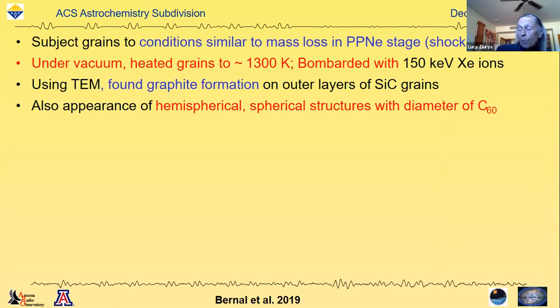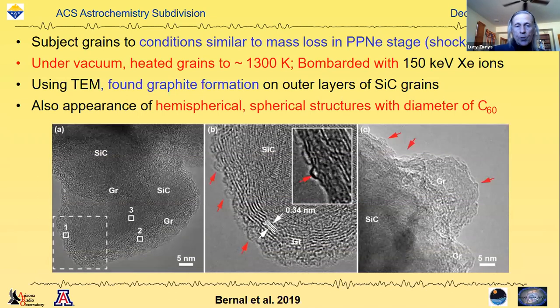So what did we want? Basically, what we wanted to do was subject those grains to conditions similar to what happens in the protoplanetary nebula phase, with shocks and high temperatures and so forth. So under vacuum, we heated our analog grains to 1300 degrees quickly. We also bombarded them with some ions. And here are our results. On the left, you see silicon carbide and you can see striations on the edge of it. That's the formation of graphite.